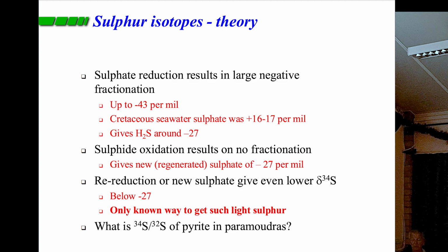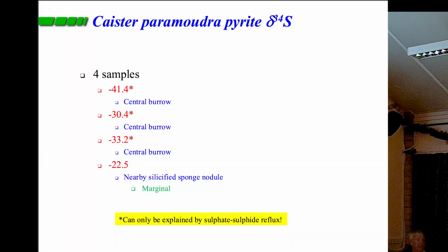So if I go and measure the sulfur isotopic ratio of the pyrite in the centre, if I see values that are less than minus 27 per mil, it proves that this sulfide-sulfate reflux is occurring. So I went and analysed some samples. I analysed 4 samples, 3 from the central burrow. You can see all of these are isotopically very, very light. In fact, they're so light, it can only possibly be caused by the sulfide-sulfate reflux mechanism. So, that's how they're forming.